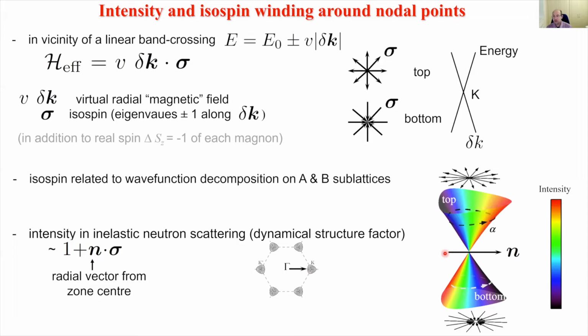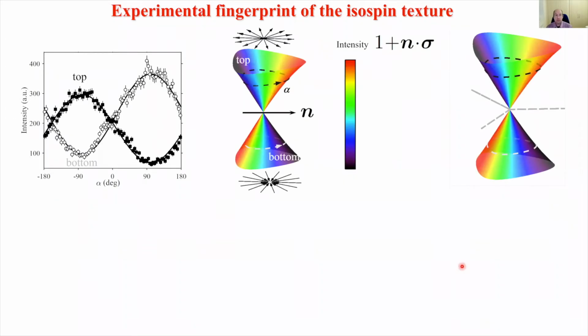So in this picture here, if we represent the characteristic vector n like this, now the isospin for the states in the top band is radially out at every point. And so we expect strong intensity, this red region here, where the isospin is parallel to the n vector. And then if we move around, when the isospin is anti-parallel with the n vector, we're expected to see cancellation under ideal conditions. And then the intensity to wind back up again. And to be exactly opposite for the bottom band, to be 0 there and maximum on the other side. So that's the physical interpretation of the intensity modulations that we see in the data, is due to the isospin winding around the nodal point and being in opposite senses for the top and bottom band.